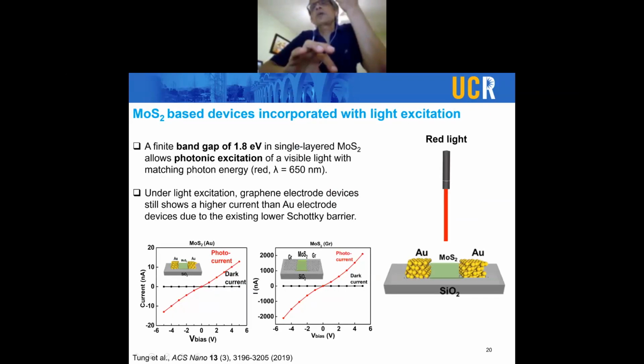A second advantage we wanted to take of the property of MoS2, its low band gap, was to use photo gating as opposed to the back gating or electrical gating or ionic gating, which is the other form of gating used in biosensing applications. And MoS2, as I said, has a low band gap of 1.8 electron volt, and the photonic excitation can be easily achieved with red light. In this case, we used an LED of red light corresponding to 650 nanometers wavelength.